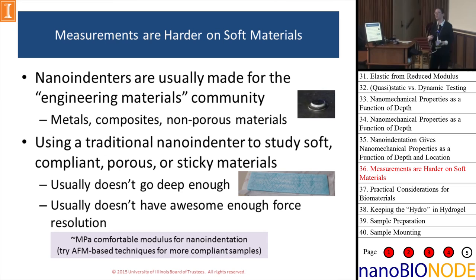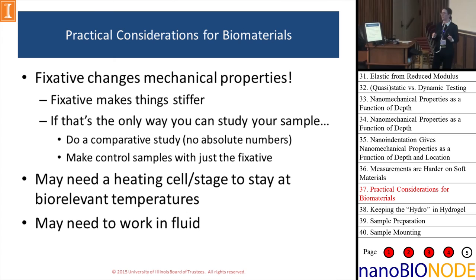This is traditional materials science. If you're doing soft and sticky stuff, this might not be the best designed instrument for you. You might want to try micro indenters or large scale testing like DMA or AFM based techniques. If you're doing biomaterials, like Luann said yesterday, fixative changes mechanical properties.